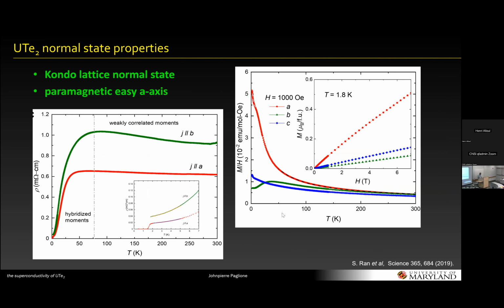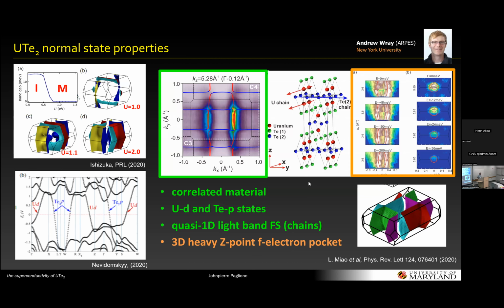So the basic properties are such that it's a heavy fermion material. It has somewhat Curie-Weiss-like behavior at high temperatures. It seems to coalesce into some heavy fermion state at low temperatures. It's not unlike the other uranium superconductors. The band structure was studied from the beginning, of course, and it was recognized early on that even to get a metallic state, you have to turn up the correlation strength of U in DFT calculations. Otherwise, you get an insulating state. So that's not unusual for F electron systems.